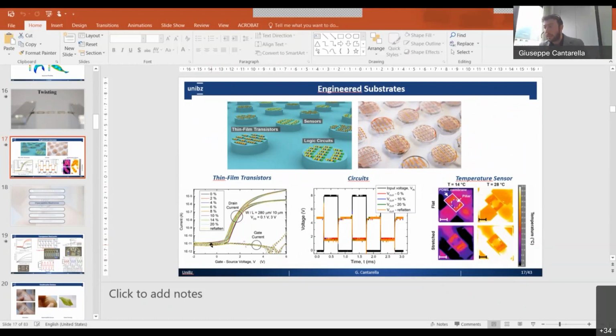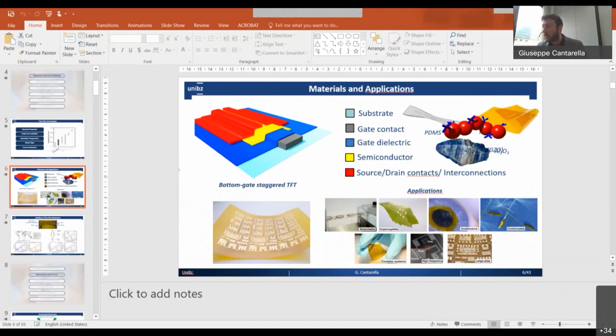Another parameter that could be very important is, for example, what you see here, the gate current. The gate current is the current passing through the aluminum oxide in our case. So it's the current that goes from the gate, through the dielectric, and reaches the source. Clearly, this current has to be as low as possible. Considering our expertise, we have been working with this technology for years, I would say even more than 10 years. We know that the aluminum oxide that we deposit guarantees a gate current that usually is in the picoampere range.